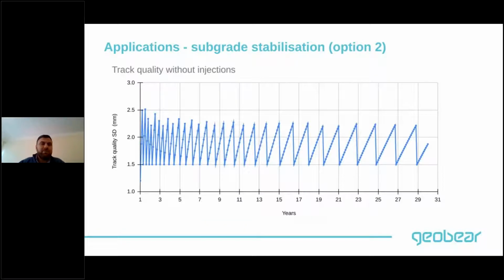Just to give you an example, I've done some analytical modeling on how the track geometry would respond for such a railway track. And I've looked at a 30-year life of the track. If you've got a track built on a soft subgrade that has a modulus of 4 MPa at 100 miles an hour or less, you're going to end up with quite a poor track quality, and your track is going to keep deteriorating. And this graph shows the track quality versus time. That's the equivalent of the CCQ on Network Rail. So that's your standard deviation charts. And you can see that in many instances, you're going to have to tamp quite frequently.